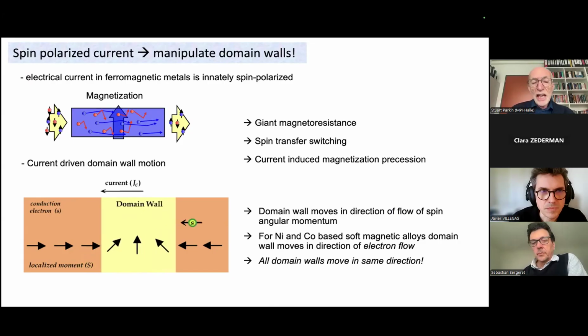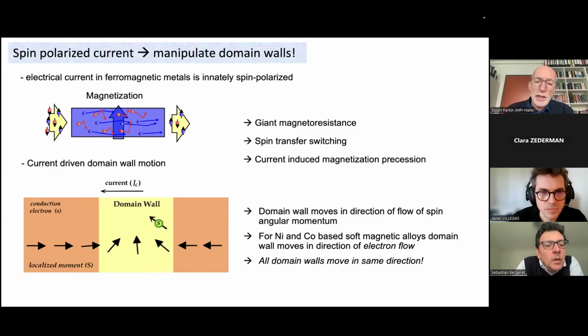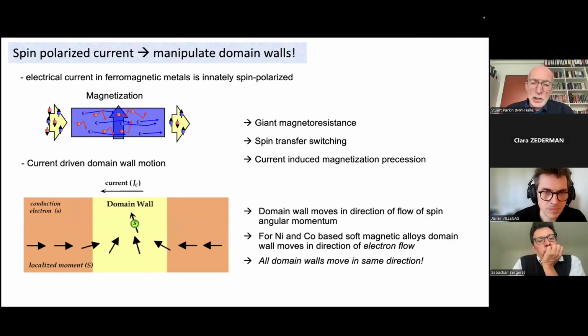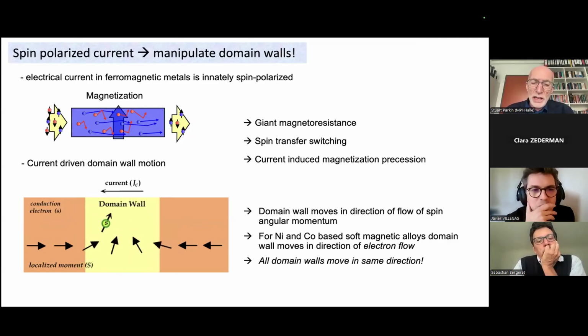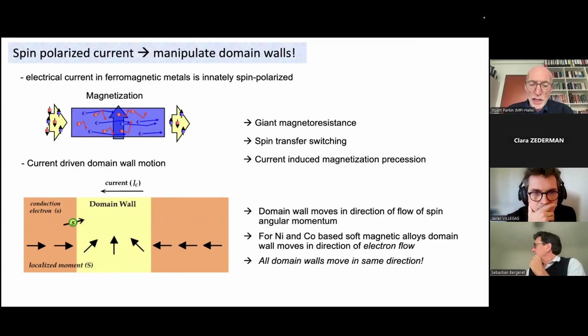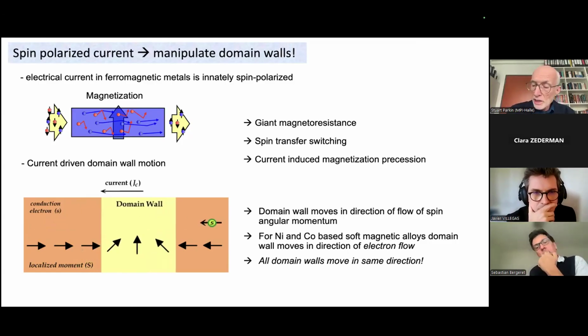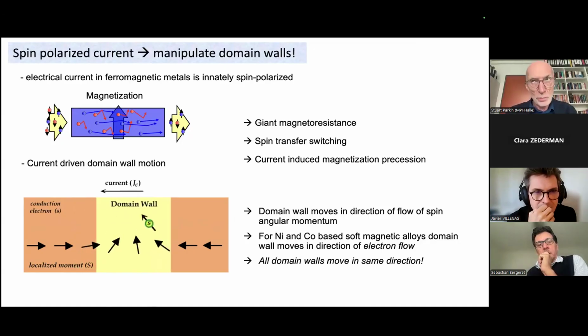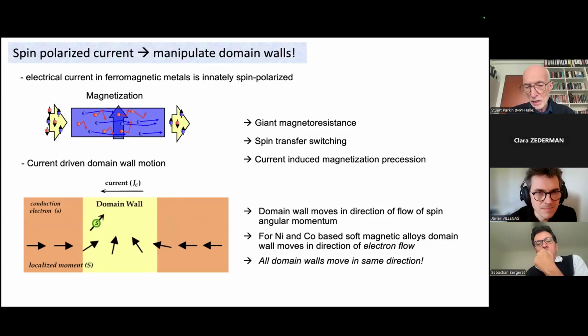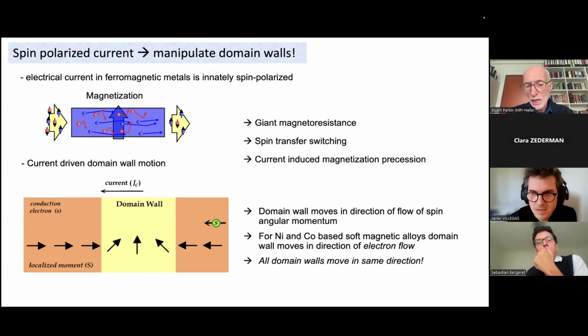So shown on the bottom left is a cartoon of a domain wall. And in this case, the magnetization in a wire is pointing to the right on your left-hand side, and to the left on your right-hand side. In between is the domain wall, which on the nanoscopic scale looks like something with mass and momentum. And as shown in this cartoon, the conduction electron, which is spin polarized, as it passes across the domain wall, it will adiabatically rotate its spin and transfer one quantum of spin angular momentum to the domain wall. And the concept is if we have enough spin angular momentum, we can basically cause the domain wall to move.